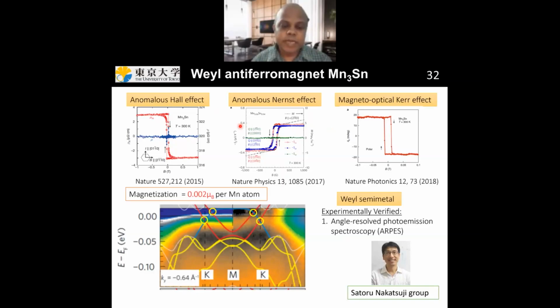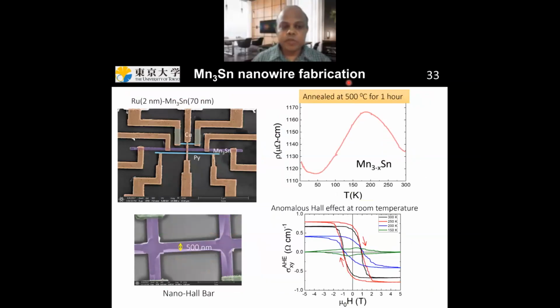And this Berry curvature can explain all these large transverse transport effects that we observe in our experiments. Since we know that large Berry curvature can also produce a large spin Hall effect, that was my main motivation to study spin Hall effect in this material, to check whether Mn3Sn also produces a large spin Hall effect. To do that, I fabricated this non-local spin valve device over here.